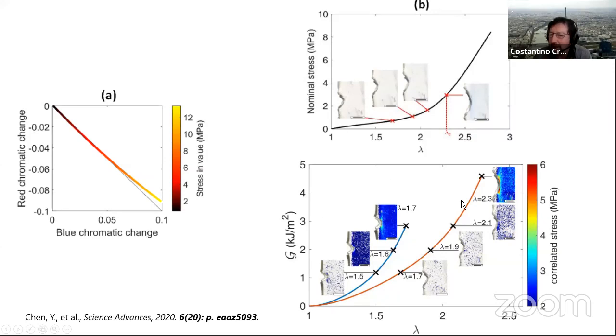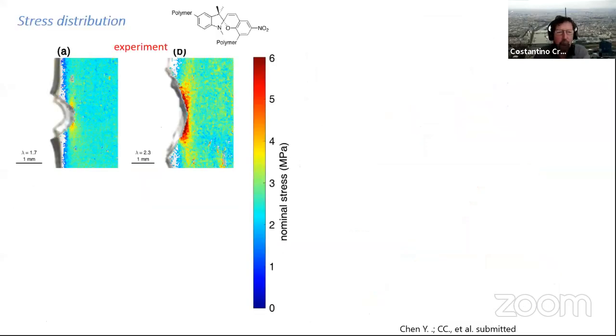Now, you, mechanician, will say, okay, but in a crack here, it's not exactly uniaxial extension. It looks like it, but it's not the same. So this was a collaboration with Rong Long, and we used not the uniaxial extension, because it's variable in this case, but the maximum stretch. So by assuming that the activation level corresponds to the maximum stretch, we can actually compare the experiment with a simulation. So this is what we're doing here.